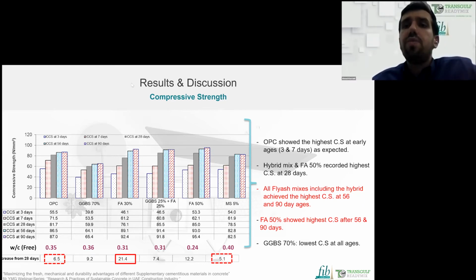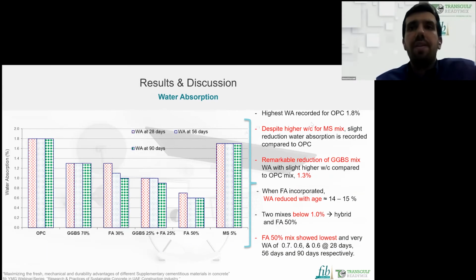Fly ash 50% showed the highest compressive strength at 56 days and 90 days, and GGBS 70% showed the lowest compressive strength at all ages. The hybrid concrete mix and fly ash 50% recorded the highest 28-day compressive strength, similarly to the 50% fly ash concrete mix. And the increase from 28 days was recorded, the highest for the 30% fly ash replacement.